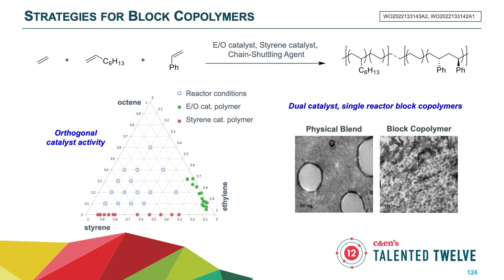And then one more example is we can use a dual catalyst single reactor approach. In this case, we have in a single reactor three different monomers: ethylene, octene, and styrene. What we're interested in doing is taking two catalysts that have orthogonal reactivity with respect to each other. What that means is one catalyst is going to polymerize ethylene and octene, but ignore styrene completely, and that will make the polyolefin block in this block copolymer. The second catalyst present in the reactor will primarily polymerize ethylene and styrene, and that will be responsible for making, in this case, the syndiotactic polystyrene block present in this block copolymer.